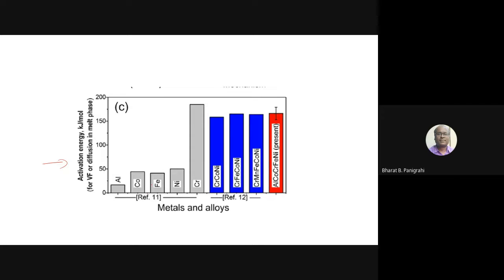Some of the data has been taken from literature. This is the coefficient of viscosity and activation energy for viscosity. For aluminum, if it is formed as liquid, this is its viscosity value. If it is cobalt liquid, just at the melting point of the metal, these are the viscosity levels. Chromium, these are all pure element liquid phases, so it has a coefficient of viscosity with activation energy somewhere here. These are the three blue lines.